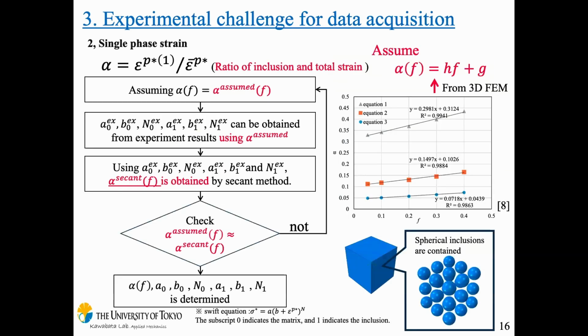Okay, next process is to get the single phase strain, and now we define the parameter alpha. The alpha means the ratio of inclusion strain and total strain, and we conduct a 3D tensile simulation using the FEM, and we confirm that there is a linear relationship between the inclusion volume fraction F and the strain ratio alpha. So we assume that alpha can be expressed as a linear function of F like this.